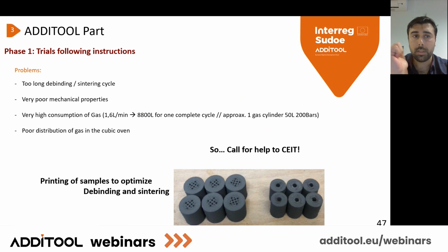So we have a too long debinding and sintering cycle. We have very poor mechanical properties and very high consumption of gas, about 1.6 liters per minute. And the complete cycle is about one gas cylinder of 50 liters at 200 bars. And we have a poor distribution of gas in the cubic oven.